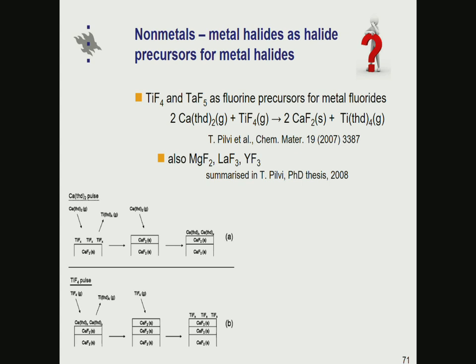There is an exchange reaction which for sure results in deposition of calcium fluoride that we analyzed inside out. And our speculation is that the byproduct is simply a titanium THD. It may also be some heteroleptic form of titanium fluoride and THD, we don't know that for sure. But anyhow, this is a chemistry which is very nice for depositing calcium fluoride and also other fluorides.